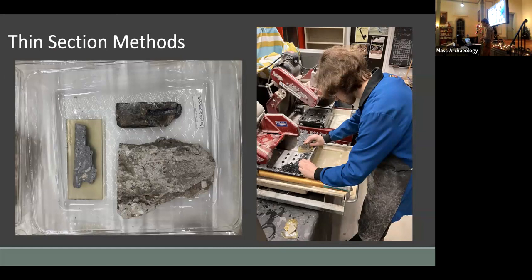So 35 tabby samples were selected as an ideal subsample for petrographic analysis. 20 of these samples were encapsulated with polyester resin under a vacuum, and when possible, an unaltered portion of these samples was preserved for future analysis. Following removal from the vacuum, the samples were placed in the fume hood, allowed to cure for 5 days, after which they were placed in a drying oven and baked for 24 hours. After the samples were removed from the oven, they were sectioned using the water-cooled diamond saw, as you can see here on the right, in preparation for thin sectioning.